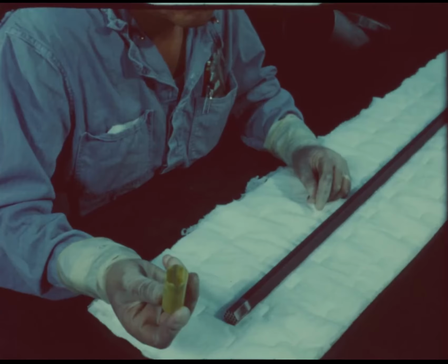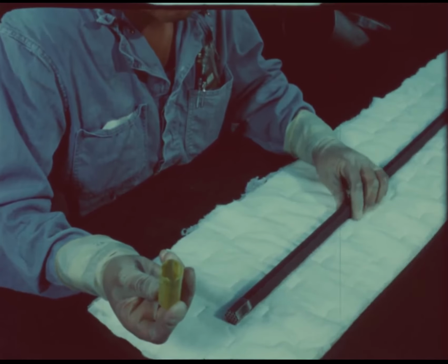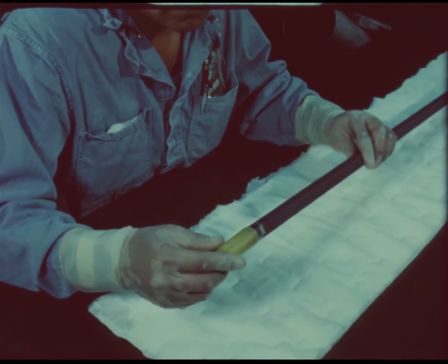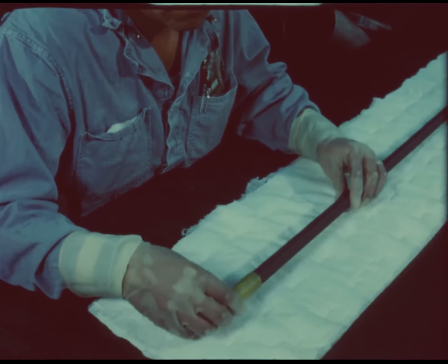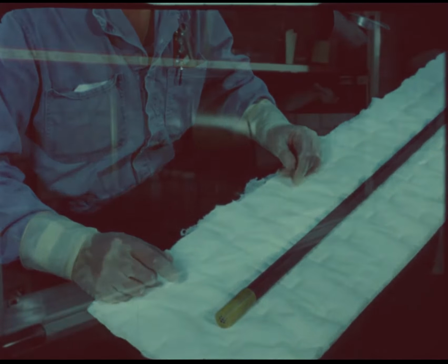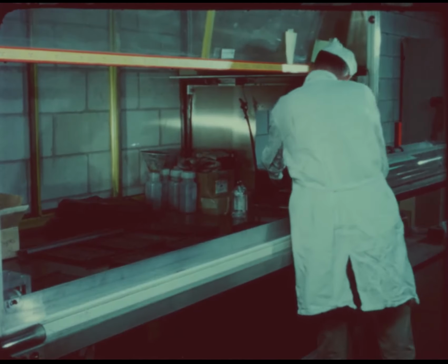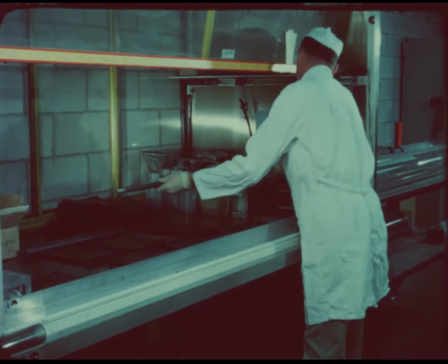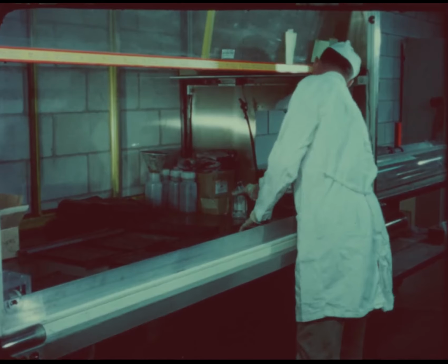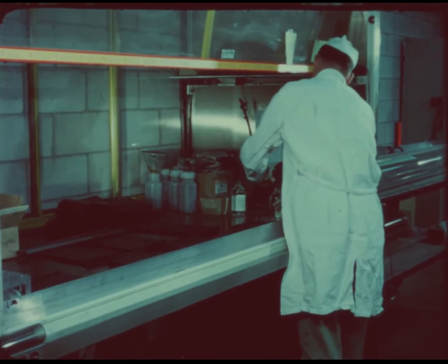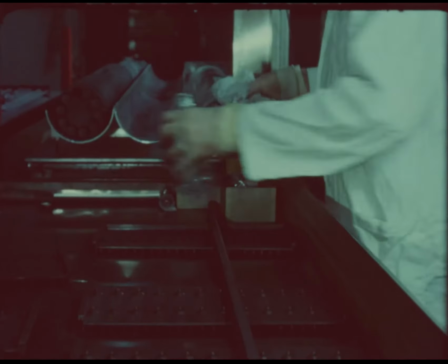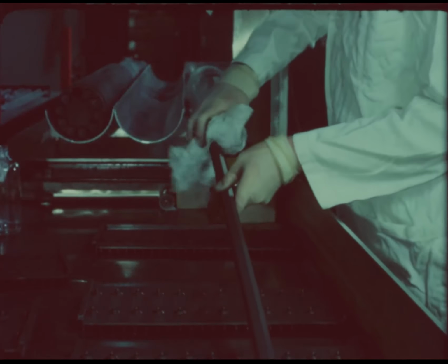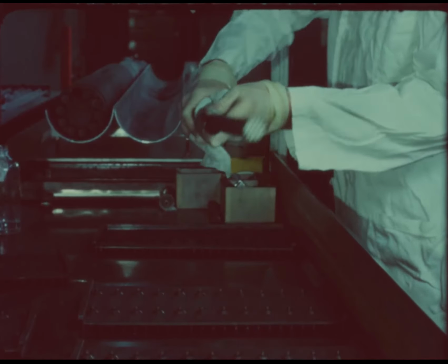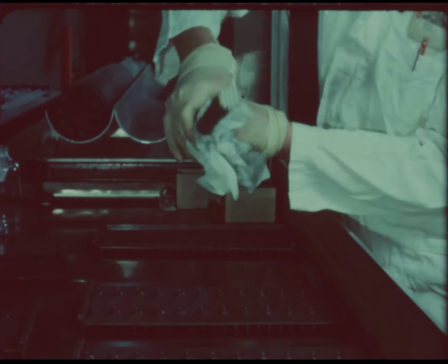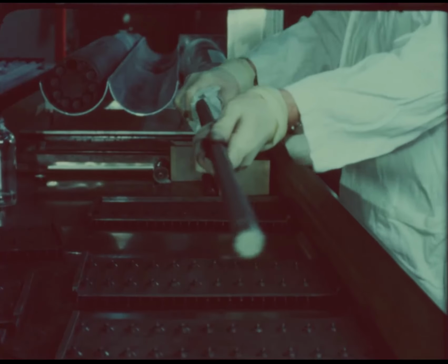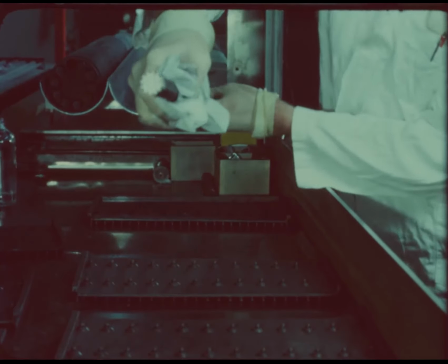But with these improvements, the most prevalent cause of rejection of fuel elements and support blocks is still chipping of the niobium carbide coating. Why does this happen? Investigation into the causes of damage to the coating seems to indicate that generally no single person or group of persons is wholly responsible for the damage. Rather, the elements that are rejected have received a series of bumps or knocks that cause no observable damage at the time, but which contribute to and finally bring about the chipping that causes rejection.